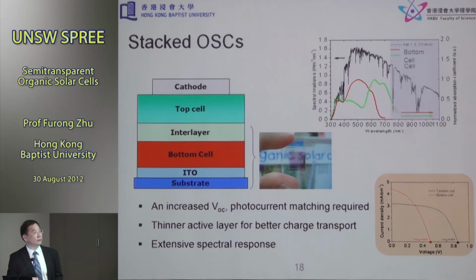Okay, so now I'll move on to how to tune and optimize semi-transparent organic solar cells. Here is the cross-sectional view of a stacked solar cell, a tandem solar cell. Essentially you have glass, indium tin oxide as a transparent electrode, one subcell, an interlayer, a top cell, and then a reflective electrode. If each subcell responds to different parts of the solar spectrum, then the stacked cell will have a broader response to the solar spectrum, and therefore a higher efficiency is expected.